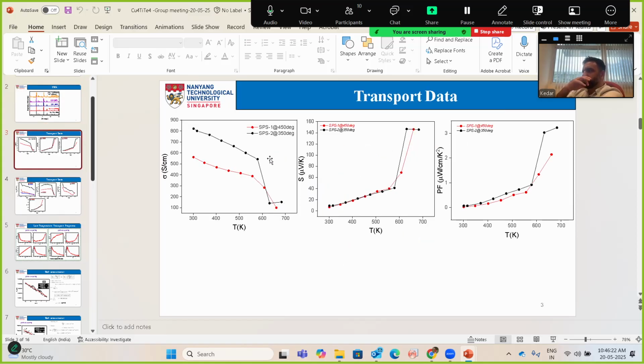Because let's look at the thermoelectric data, right? Okay, let's go to the data now. Thermoelectric data. Need to understand. What kind of phase transition? The point is that it's supposed to be copper telluride, but it's a very minority phase in the sample, like 14% or 12%. So it should not give you such a big change in either the transport data or the DSC. So that's the mystery, right?